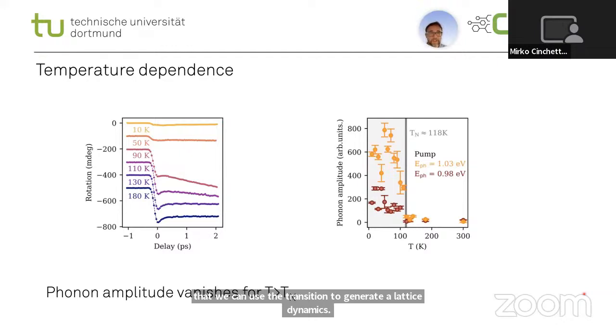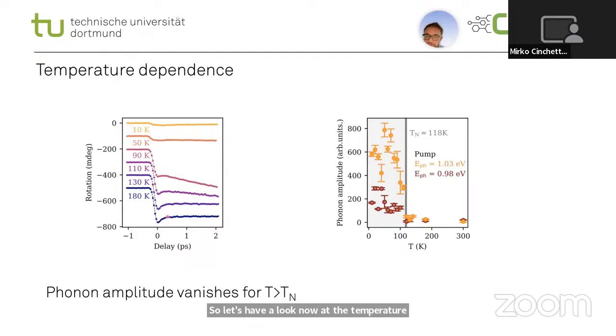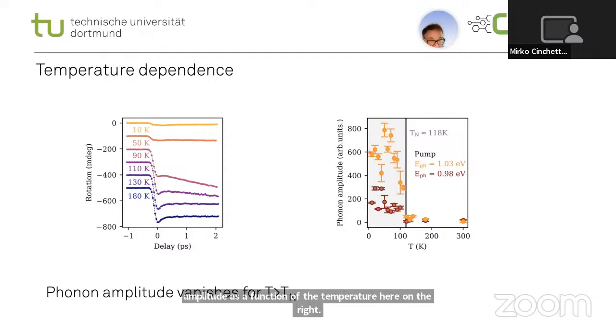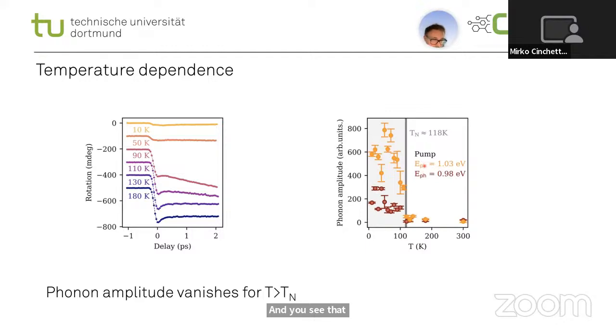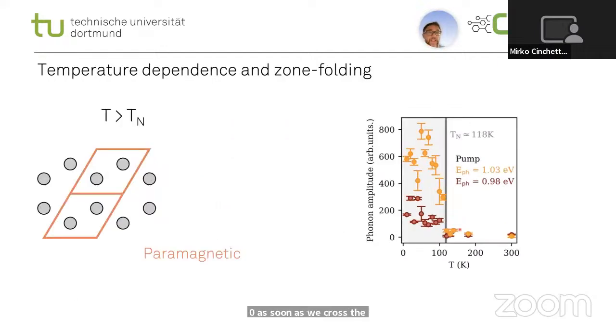Let's have a look now at the temperature dependence. Now we measure the same curves as a function of the temperature, and plot the phonon amplitude as a function of the temperature here on the right. You see that for two different photon energies, in both cases the amplitude goes to 0 as soon as we cross the Néel temperature. So somehow these phonons feel the magnetic state of our crystal.